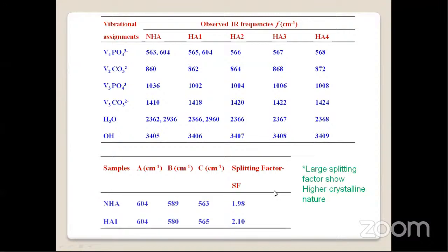So then another important use of finding the splitting factor is that whether these materials are getting crystallized or not. There is a correlation between the powder X-ray diffraction and the Fourier transform infrared spectroscopy. In the case of powder X-ray diffraction, as I told you earlier, when you are increasing the temperature, there is an increment of crystallinity behavior. At the same time, the same can be reconfirmed by spectroscopic studies like FTIR.